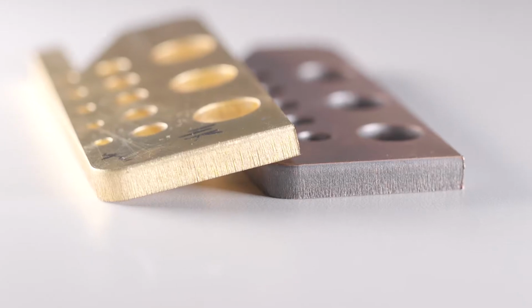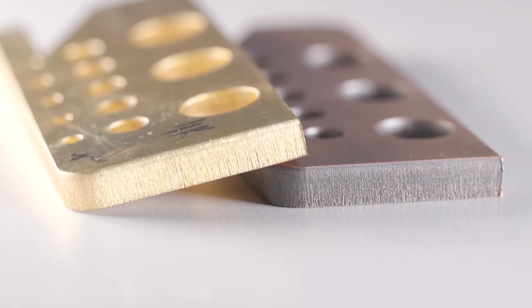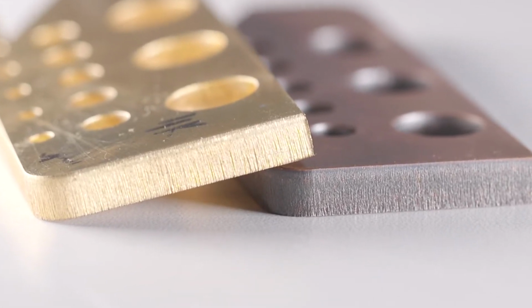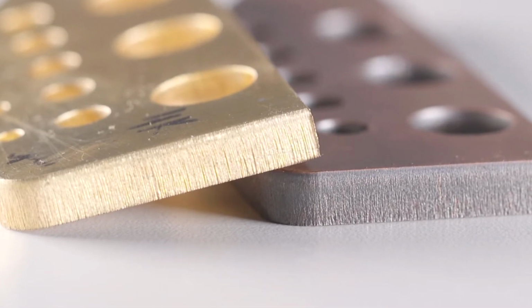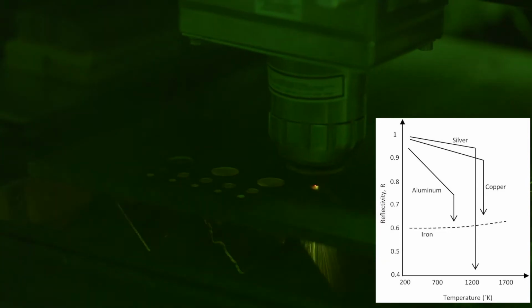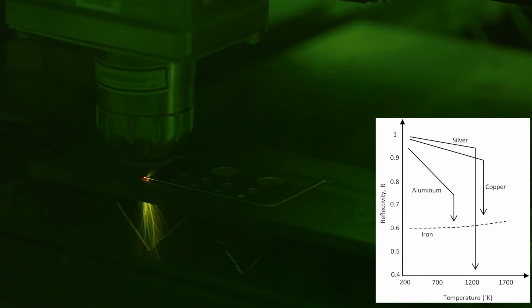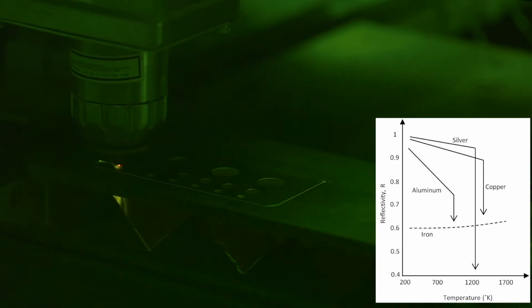Copper and brass are good reflectors and therefore bad absorbers of infrared laser light. Their reflectivity, though, does not stay the same with the temperature. It changes with temperature. For example, copper's reflectivity is about 95% at room temperature, but after melting, it drops down to 70%. So therefore, copper and brass and some other reflective metals are much more absorbent of the laser light when they are in the molten state.